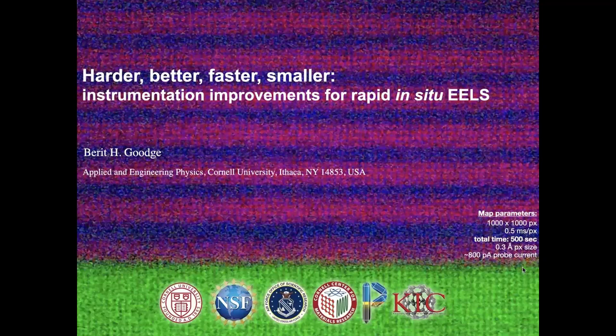This EELS map that I'm showing here on the title slide is one that we were able to acquire this fall using some of the new instruments that are right at the tail end of being installed here at Cornell, which I'll talk about at the end of the talk. This is a 1,000 by 1,000 pixel EELS map running at about 500 microseconds per pixel. The total SI time for this, for people who are familiar with atomic resolution EELS, is a very large field of view map, and is actually just on the order of a few minutes with a very small pixel size. And we're able to do this with a very high probe current.